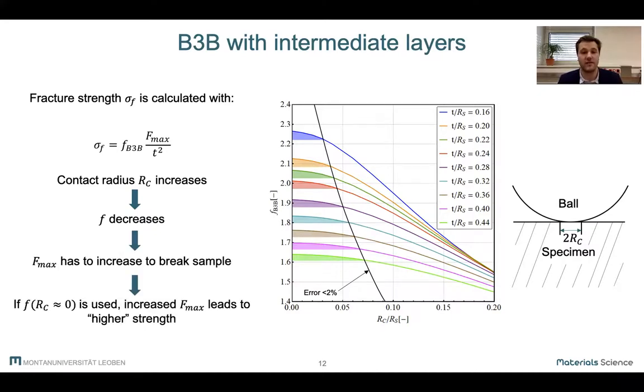However, if we still use the factor f for an ideal point load, about here, then the increased maximum load leads to a seemingly high strength, which explains why we found results on the previous slides.